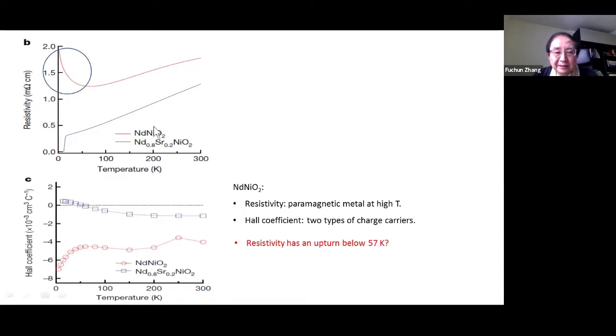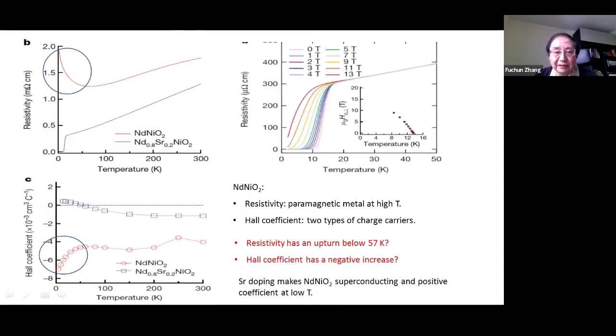The resistivity, as you can see, is a paramagnetic metal at high temperature, with these two types of charge carriers. So the question is why the resistivity has an upturn below around 50 or 60 Kelvin, and the Hall coefficient has a negative increase. The upper right panel shows the resistivity as a function of temperature for various magnetic fields. This is zero field, and the superconductivity is suppressed or destroyed by magnetic field. So this is the phase diagram, superconductivity and normal state.